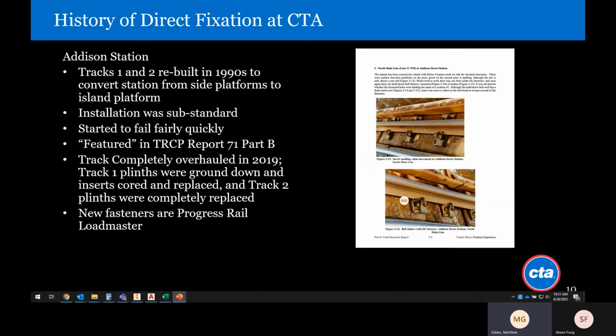So track one, the plinths were ground down, and we kind of used this as a test bed. So on track one, we ended up grinding the plinths and removing the existing inserts and replacing them with new inserts. In track two, we completely replaced the plinths, and we had intended to replace the plinths on both track 1 and track 2, but contrary to what the drawings had shown, it appeared that the plinths were poured in as part of the deck and not a separate pour.